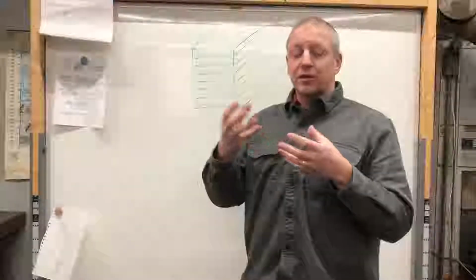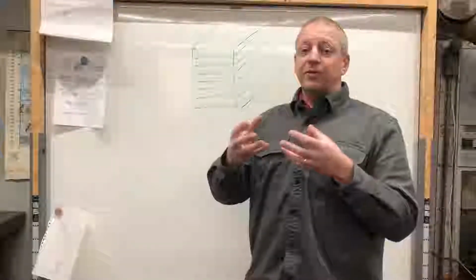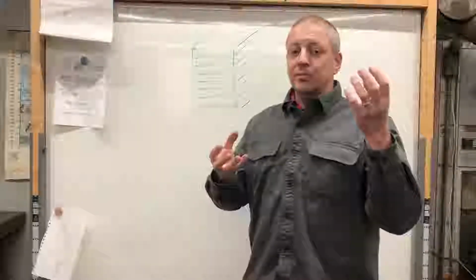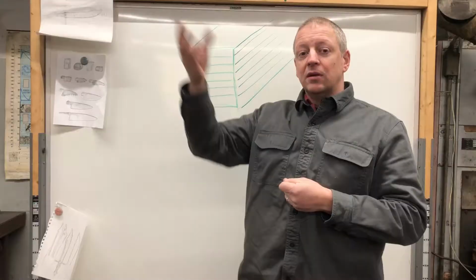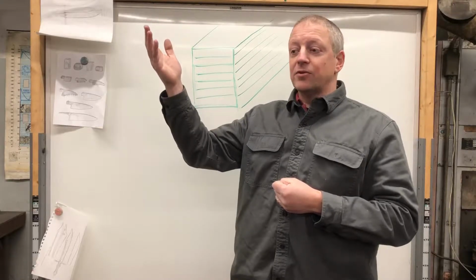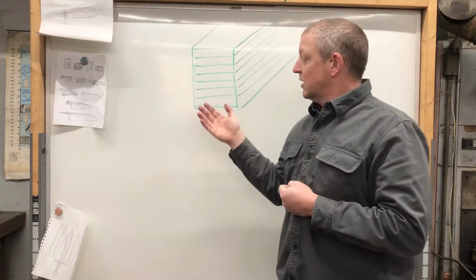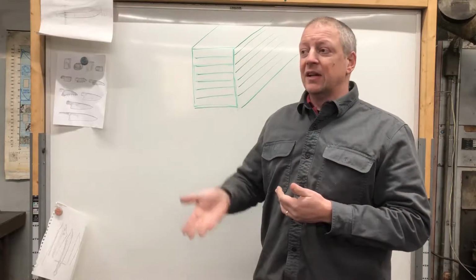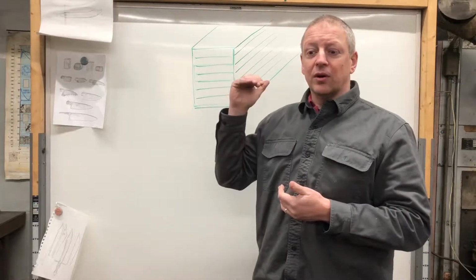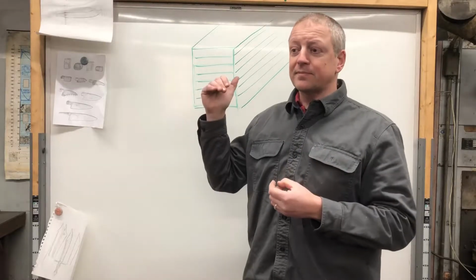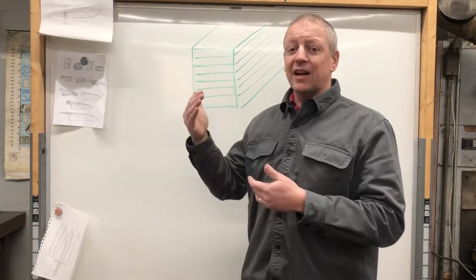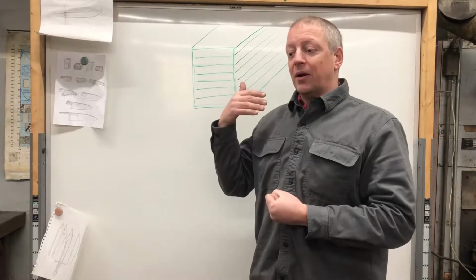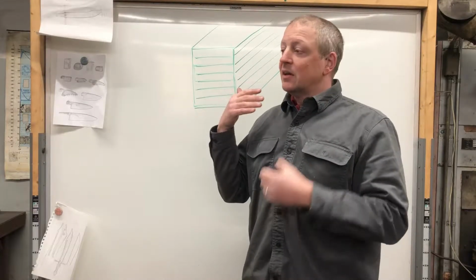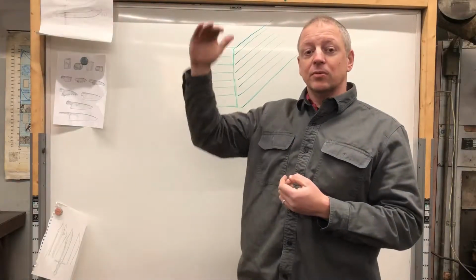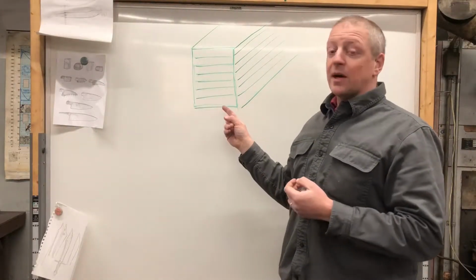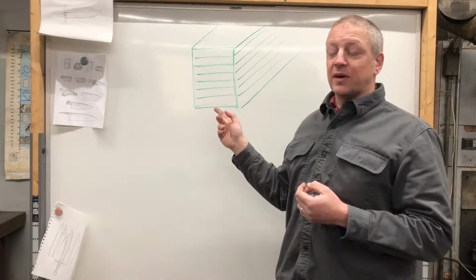One carbon atom comes to the surface, FeO breaks down, you get pure iron, and carbon monoxide floats away as a gas. And this is part of why the hotter your steel is, for the most part, the easier it is to weld. The hotter it gets, obviously it's softer, but also carbon migration becomes exponentially faster as you move your temperature up. So it becomes much easier for carbon to make its way to the surface.